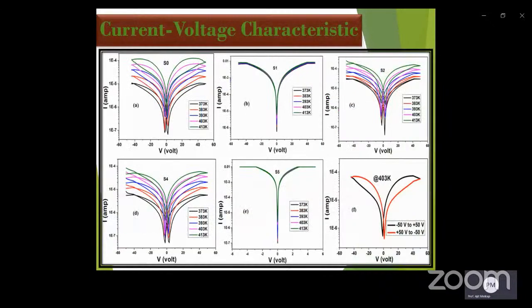A clear electric hysteresis in current voltage behavior has been observed for all samples except S1 and S5. Initially, increasing voltage from 0 to 50 volt, the current value is high, so a high conducting state has been observed. In this state, a local conducting path of low resistivity may be generated.